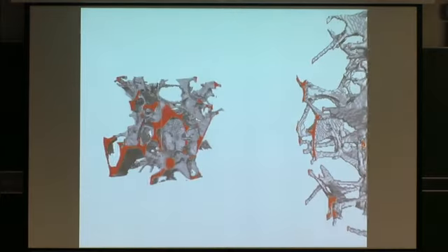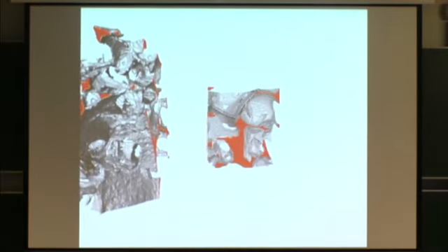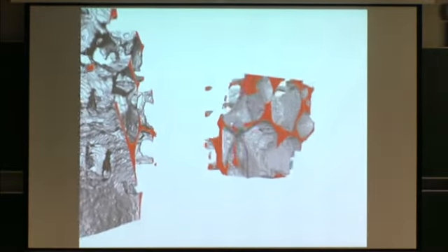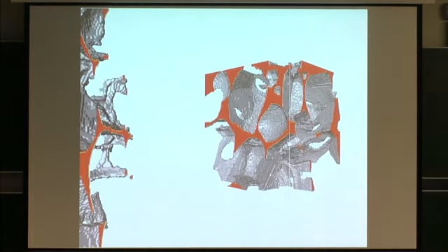And 20%. So what you see really is melt at low 2%, all right? So they mostly concentrate on the triple junctions. And with higher melt fractions, I call them spill over to the grain boundaries, all right?